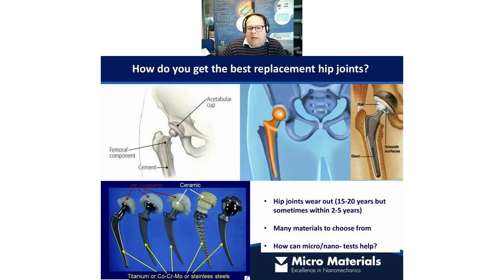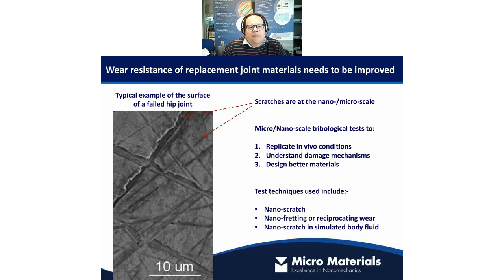And so how can nano and micro testing help with this? Well, if we take a look at an actual hip joint ball surface here, you can see these scratches in the surface. And here we've got a 10 micron scale bar. So what you can see is we've got scratches in this surface from a recovered failed hip joint, which are at the scale of the types of scratch tests or wear tests that we would perform using a nanoindenter or a nano scratch test device.